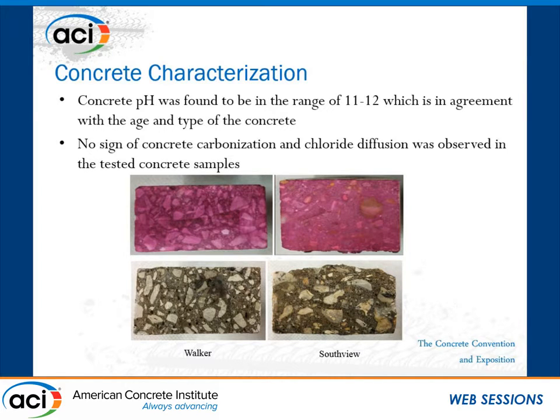We also performed the chloride diffusion test and carbonation depths, and we found that there was no carbonation in the concrete cores and also no sign of chloride diffusion. While having no carbonation could be an ideal case for steel rebars because it postpones the corrosion, it is a worse situation for the GFRP bars, because the alkalinity of the concrete is higher and there is no carbonation. It provides a more severe case for the GFRP, because GFRPs theoretically are supposed to be weak in alkaline environments.